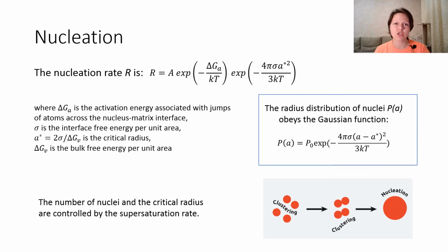The first stage is the nucleation, which means the formation of a very big number of small nuclei. Here we have the very beginning of our growth process. That's why we can consider the concentration of ions that will be used in our future crystals as constant. The nucleation rate, or the velocity of forming of new nuclei, can be written in this expression.